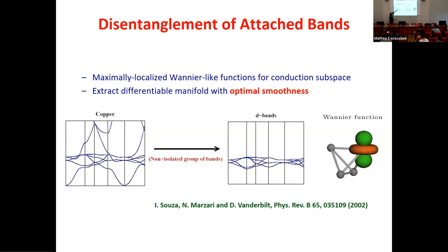That is, we always say, well, the band structure of copper is given by five flat d bands, localized, with very little overlap, and one very dispersive parabolic s band coming from the 4s electron. So 3d flat, 4s parabolic. How do we separate this spaghetti? How do we extract these five d bands? Well, that's at a certain level mission impossible. That is, there are always going to be somewhere, in some corners of the Brillouin zone, areas where all the bands, the five d and the one s band, are mixed together.